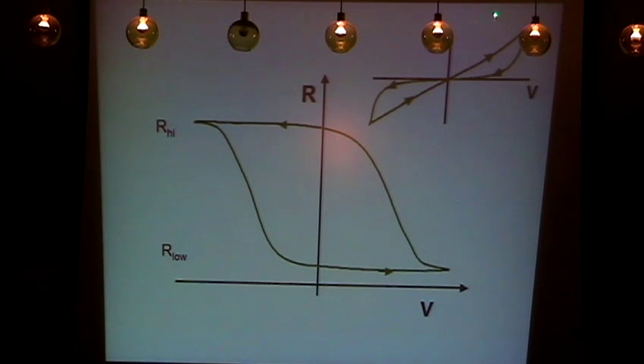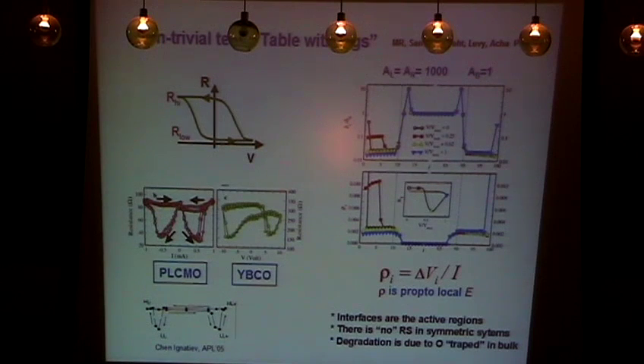Okay, before showing you the results, I want just to set up a little bit of the problem. If you have a typical IV resistive switching characteristic, when you plot R versus V for this hysteresis loop, what you get is the switching from high to low and vice versa. So this is what you expect for a simple hysteresis. Now, when you go to symmetric samples, instead of this, what we get is this odd-looking resistance versus current or resistance versus voltage loop, which looks like a table with legs. The table with legs is not a nomenclature that I invented. It was introduced by the group of Alex Ignatiev in a paper in 2005. And these are the results that motivated my curiosity in his paper. They were rather poor, but essentially correct, and certainly mysterious.